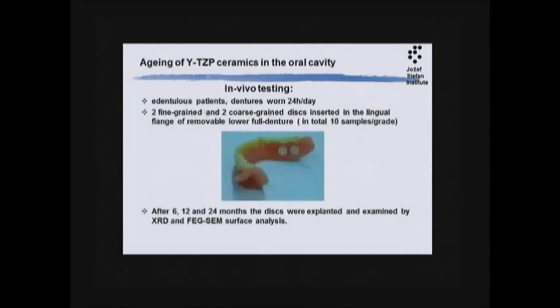In vivo, a very simple test was designed. I said, let's have a look and check the relationship established for the femoral heads. So we have implanted those small discs into a removable denture, 4 specimens into one denture, 2 on each side. We started with 10 patients, and no, we started with 5 patients, so 10 specimens per grade. The specimens were explanted after 6 months, after 1 year, and after 2 years. And I'll show you the results.